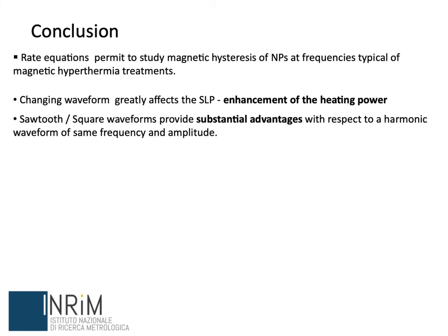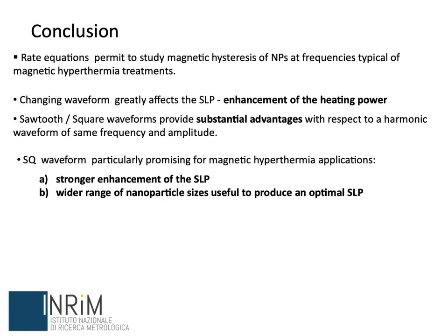We have shown that a simple change of waveform greatly affects the value of the SLP parameter. The sawtooth or the square waveform behave as the best ones and provide substantial advantages with respect to harmonic waveform of the same frequency and amplitude.